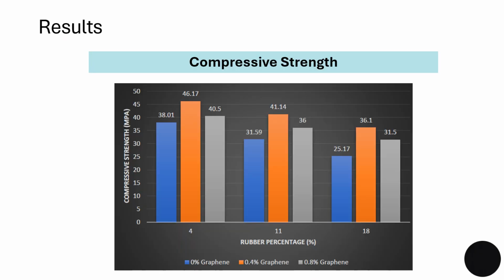Our objective is to develop high efficiency material with low thermal conductivity and at the same time with sufficient compressive strength for practical application. That's why we added two materials, rubber and graphene. Rubber was added to reduce the thermal conductivity, which is essential for energy saving, while graphene was added to compensate for the loss of compressive strength due to the addition of rubber.